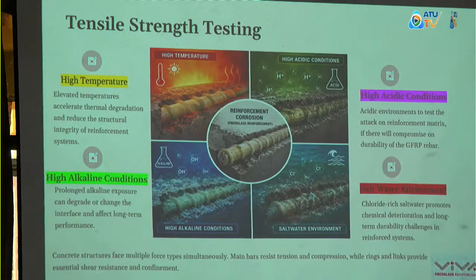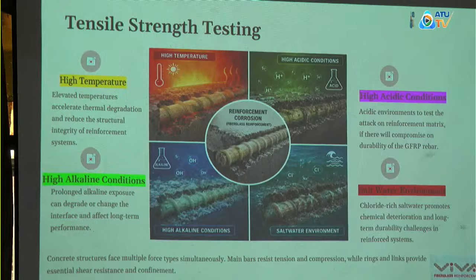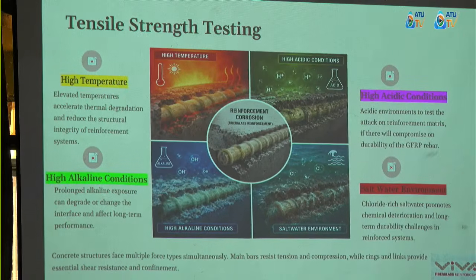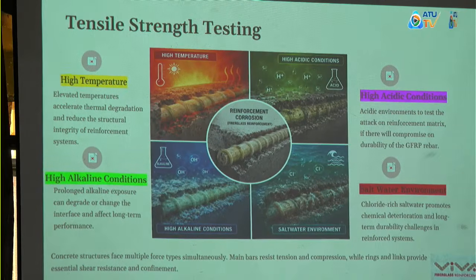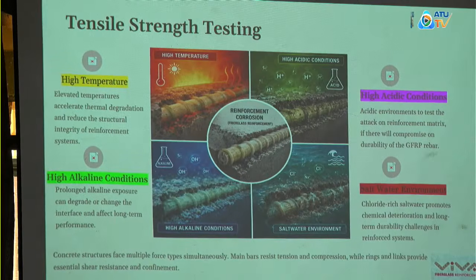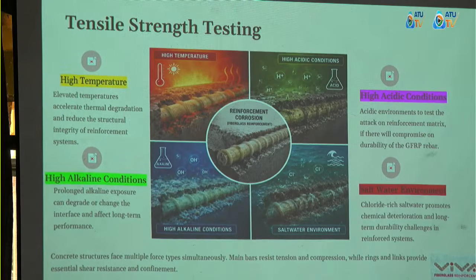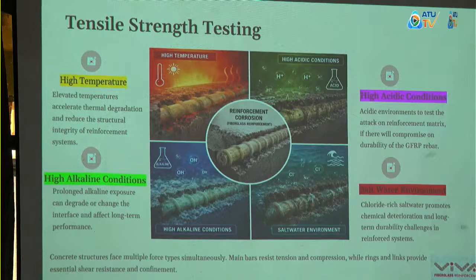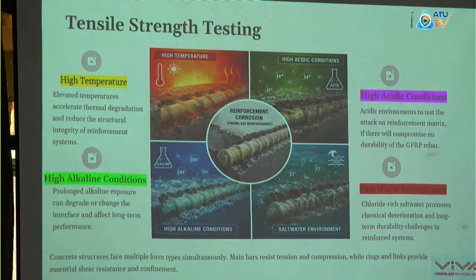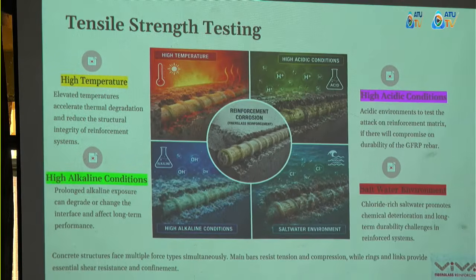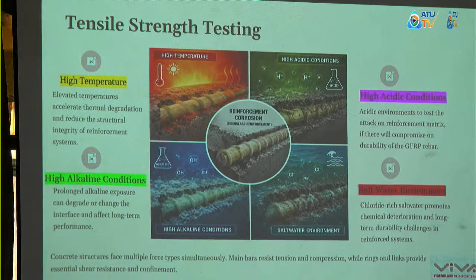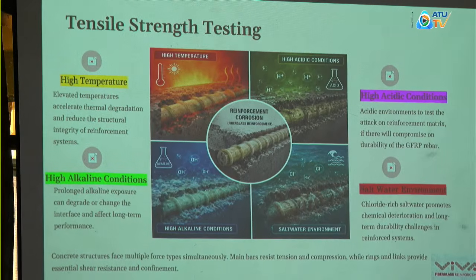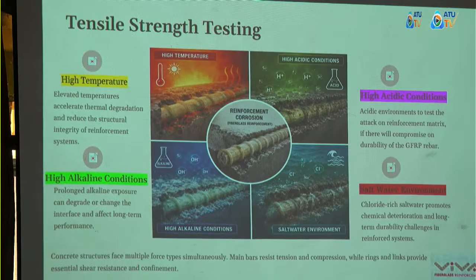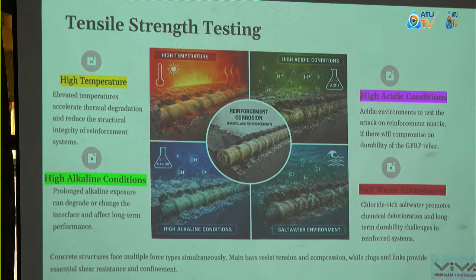And finally, I exposed it to a salt water environment, because where I'm from, a coastal island in Kenya, in Mombasa, the corrosion of the steel bars by the salt water is very high. You leave the reinforcement outside for 1, 2, 3 days and you start seeing rust on top, which in the long run affects the performance of the material.